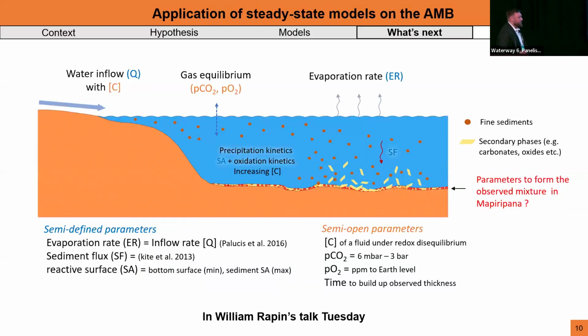At the global scale on Mars, it could also be very significant, because that would mean in some places where you think that the conditions are oxidizing but kinetically limited, as soon as you have evaporation and the right conditions, you could have transient alkaline conditions that enhance this oxidation rate. Which means that when you do modeling, for example, of steady-state lakes on Mars, that would change your parameter window where you actually get your siderites or your iron oxides. And that was in the William Rapin's talk Tuesday,